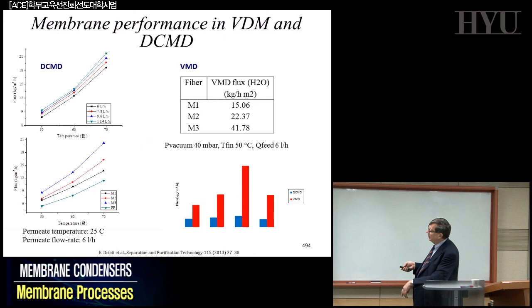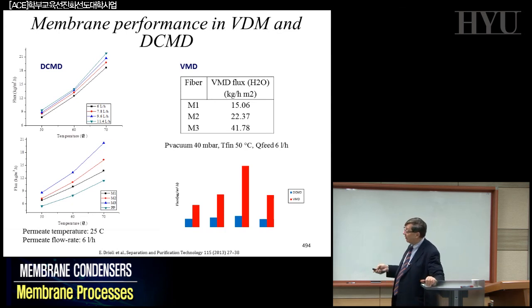Basically, these kinds of results are interesting. That is again what you expect in membrane distillation performance. You can see these membranes are going to be tested basically not in microfiltration, but in direct contact or vacuum membrane distillation. And this behavior, now you understand very well exactly what you expect. It's just the transmembrane flux as a function of the temperature, and it is not linear, because we know that in membrane distillation what we expect is an exponential behavior. That's exactly what is happening here.